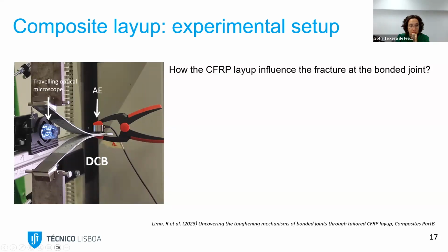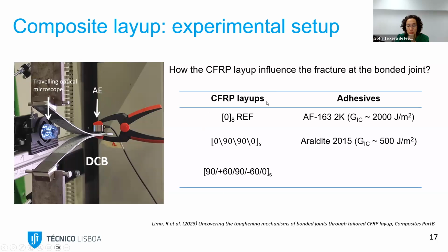And we see how the fracture propagates from the beginning, which is here, until the end of the specimen. And we changed the layup, so we used all 0 degrees as reference, a cross ply laminate, and a more non-conventional laminate using 90 and 60 degrees plies. And we also used 2 different adhesives. A very tough adhesive, which has 2,000 joules per square meter, and a low toughness adhesive, which is about 500 joules per square meter. And to check what was the influence also of the fracture toughness of the bond line.